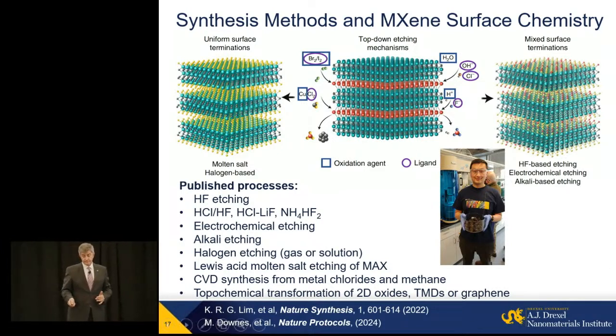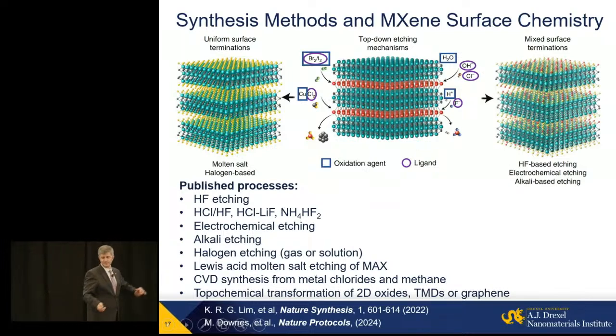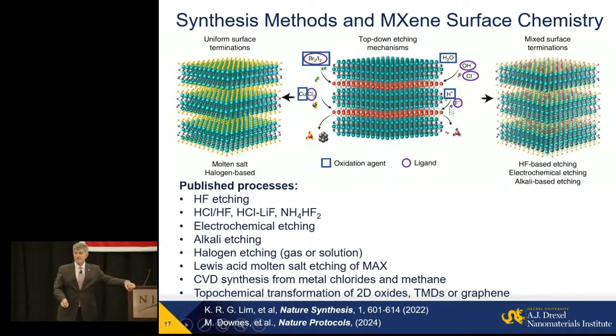This type of wet chemical etching used a mix of different salts, acids, electrochemical, alkaline. We end up with a material having oxygen, hydroxyl groups, and maybe some halogen like fluorine on the surface. They are hydrophilic. They can be dispersed in water without any surfactant because they have a high negative charge. Zeta potential is usually between minus 30 and minus 80 millivolts. So they form stable colloidal solutions.